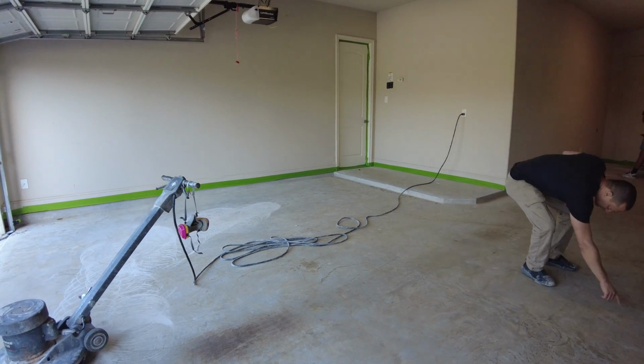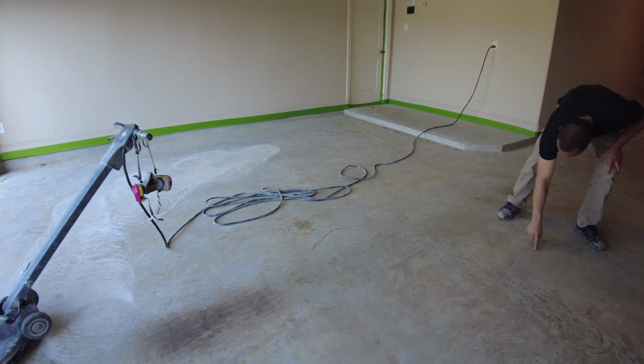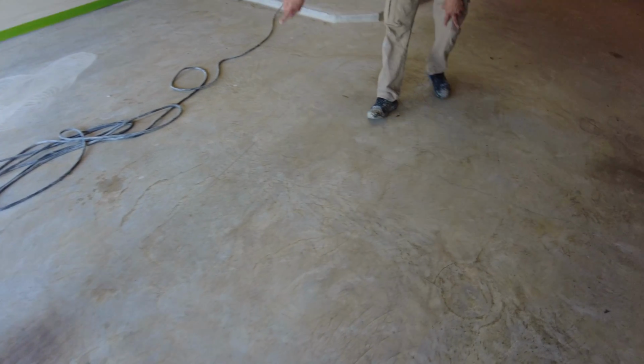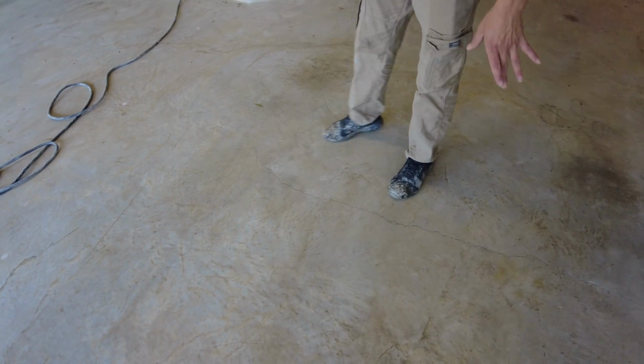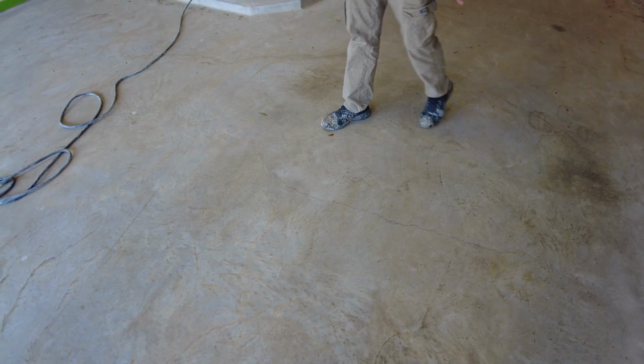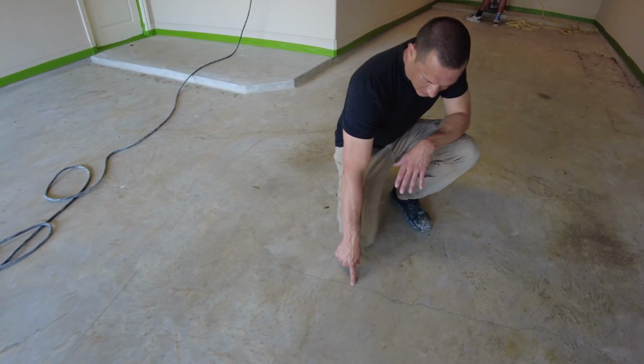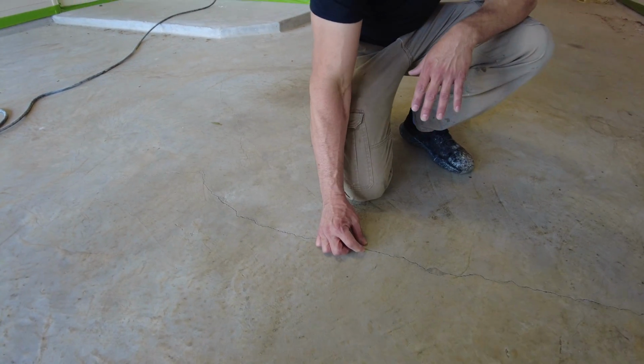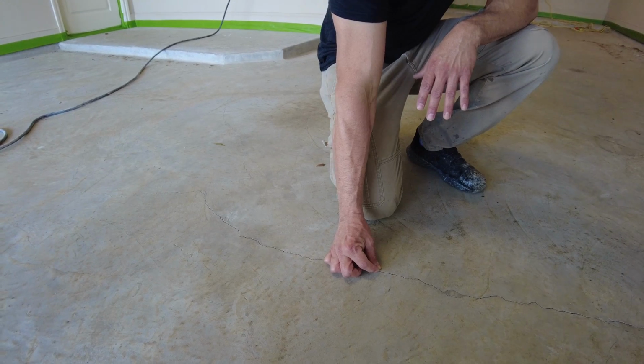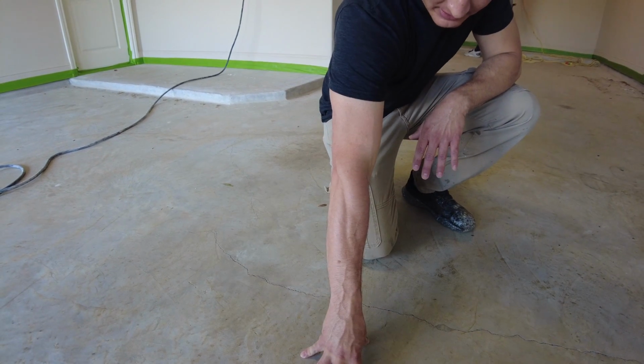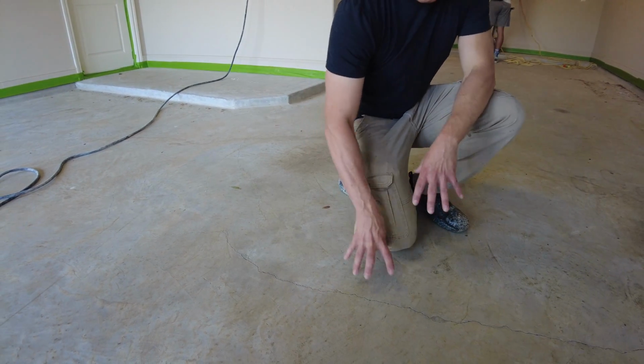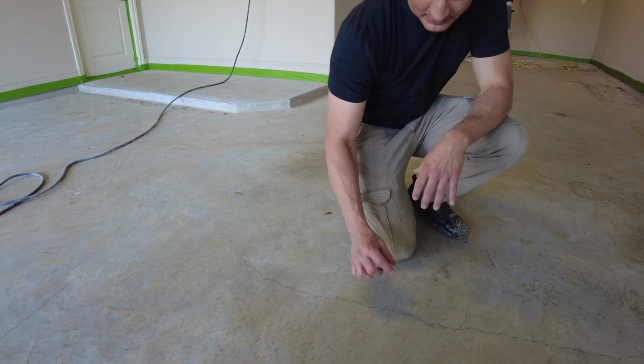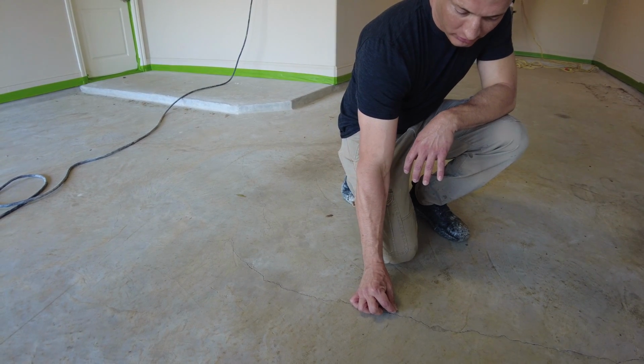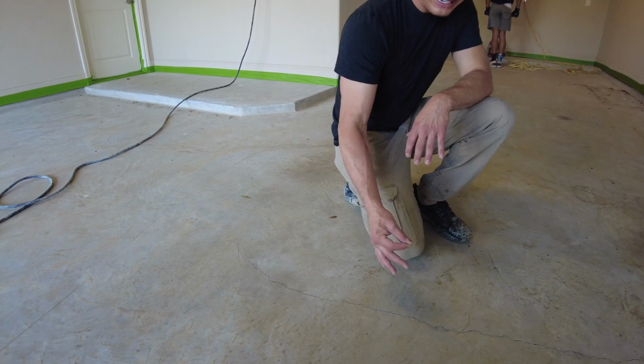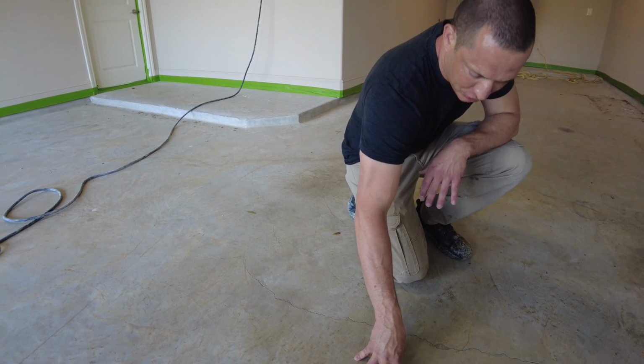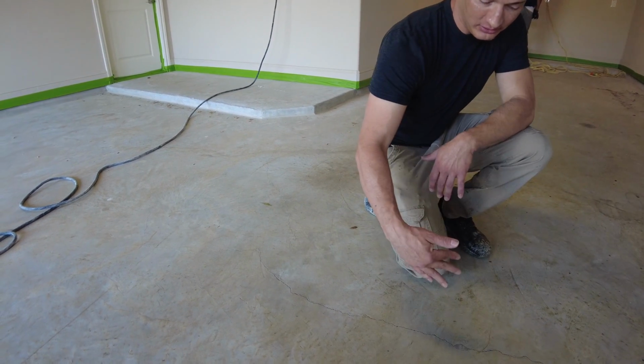We got some cracks right here. That's not good. It's not good if you're using epoxy especially. So this crack right here gets smaller when this concrete slab gets hot, because it expands, and this concrete slab expands. So that crack will get smaller during the heat of the day, and at nighttime, when this concrete slab shrinks, and this one shrinks, it gets larger.